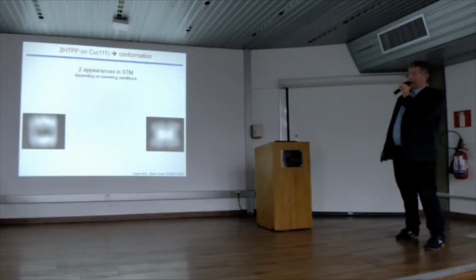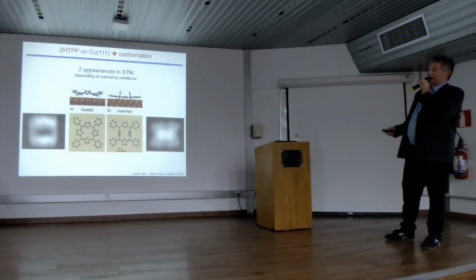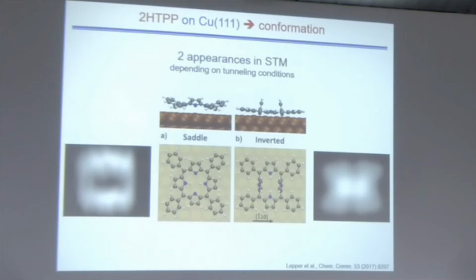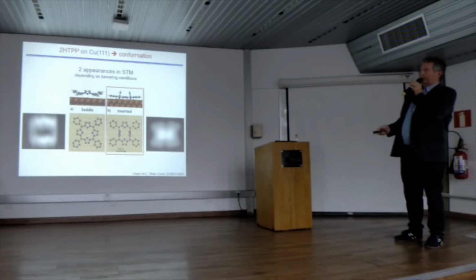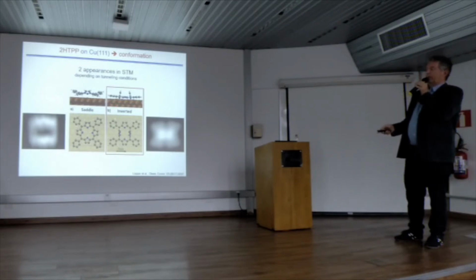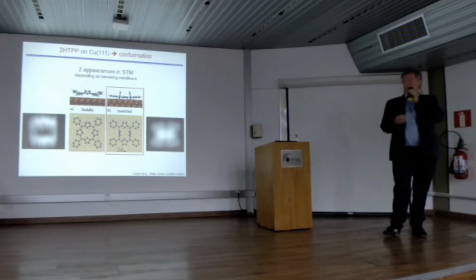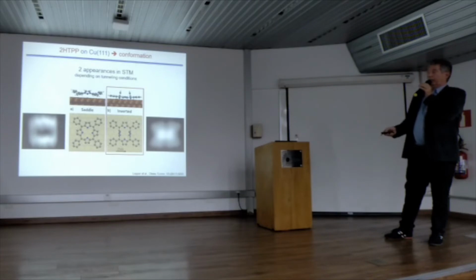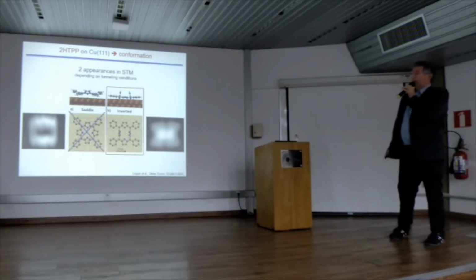And now the question is, what can we learn then from the adsorption geometry if we have these different appearances? So theory is typically of help there. You ask the theoreticians, friends that we have in Erlangen, to do a calculation on the energetic stability of the molecules on the surface. And the colleagues did that. They calculated this saddle-shaped type deformation, and the molecule looks like that. And then they calculated what is called an inverted structure. There you flip one of the pyrrole groups completely 90 degrees out of the molecular plane. And if you do the calculation, you find this is much, much more stable than this one. The appearance is the same. It's always this molecule, but we are fooled by the nature of the tip. So the stories on what I told you before are unchanged, but the appearance of the molecule could be like this or like this, and then the rest is the same. Okay, we rule out this one.